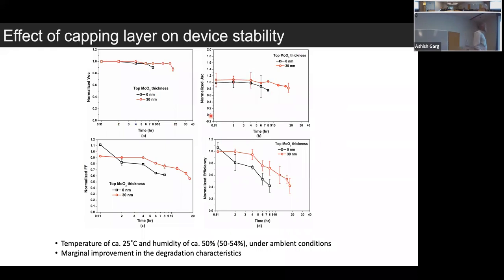Interestingly, the lifetime of these devices is also slightly better. When you put a capping layer, the lifetime is slightly improved. It's not a remarkable improvement, but it's a slight improvement in terms of all the physical parameters. Most of the drop in these devices is mainly because of a drop in the fill factor and the current. VOC is rather straightforward, it's constant. So it's because of material degradation, which to some extent can be circumvented by using these metal-dielectric-metal top electrodes.